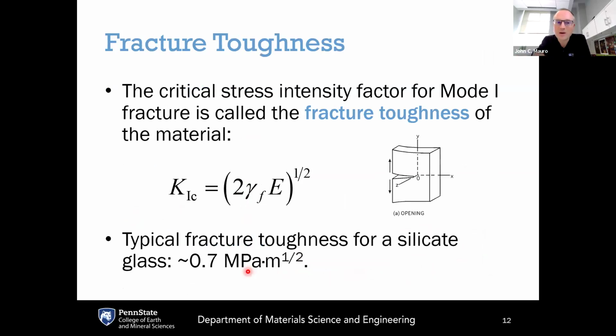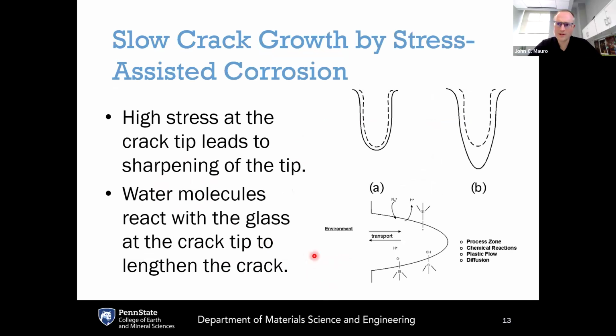What you probably most commonly see is this K1C. K1C is the critical stress intensity factor under mode 1 failure. This is more commonly known as the fracture toughness of the material. So if you see the toughness quoted, that is the K1C. For typical silicate glasses, the fracture toughness is on the order of 0.7 megapascal times the square root of meters.